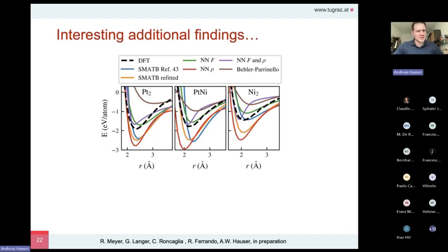And to conclude this talk now, another interesting finding, just to show you what are the limitations of such a neural network. If you let the network learn on systems that consist of 10 to 150 atoms in this mixed feature of platinum and nickel, for example, what's the prediction of these networks for the simple diatomic molecule platinum-2, nickel-2? To make a long story short, if you take the fully uninformed system, Behler-Parrinello, so this brute force network, it is not able to reproduce the DFT potential energy surface, which is in this case a potential energy curve, the dashed line. It's completely off.